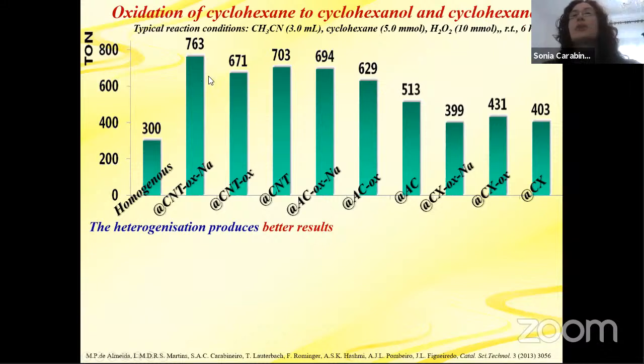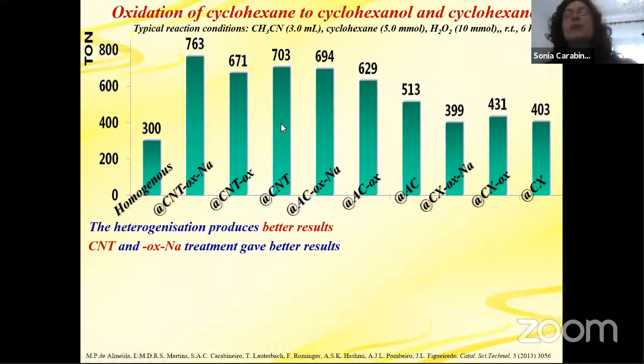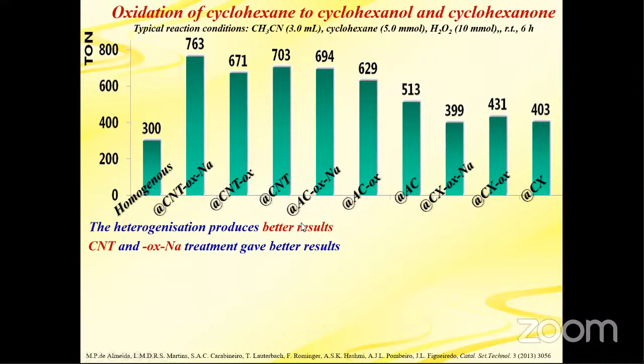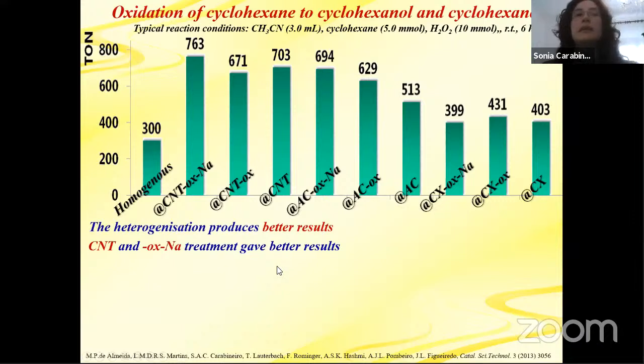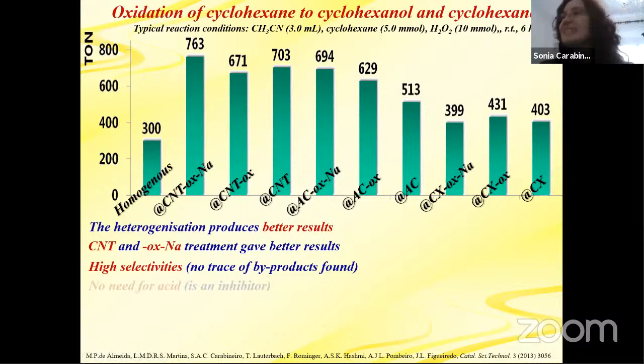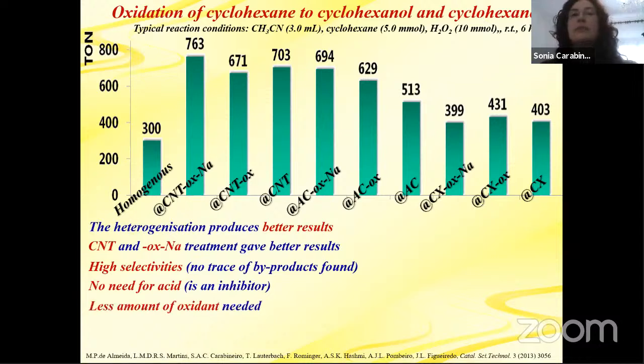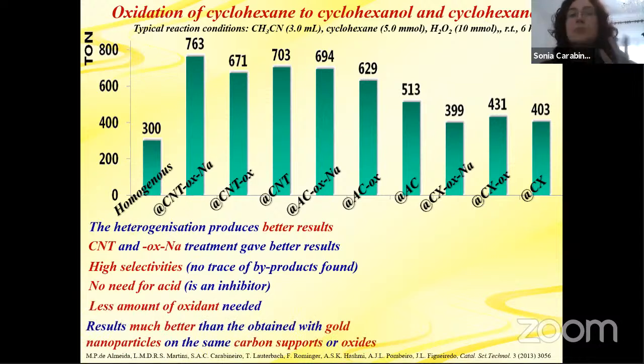heterogenized on several carbon supports, the yields were better. So carbon nanotubes gave the best results here, and this ox-Na treatment, the treatment with acid and then sodium hydroxide, gave the best results. High selectivities, no trace of byproducts, no need for acid. In fact, acid was an inhibitor, and less oxidant was needed, and the results were much better than those obtained with the gold nanoparticles on the same carbon supports and on oxides, which was quite good.